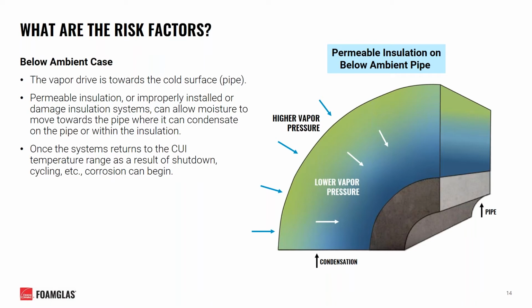On especially cold systems, this condensation may turn into ice, which, not being liquid, does not inherently contribute to corrosion. However, if the system is allowed to then warm up as a result of a system shutdown or cycling processes, that ice can then melt and introduce a large amount of liquid water onto the steel pipe, quickly becoming an environment for corrosion to take place.